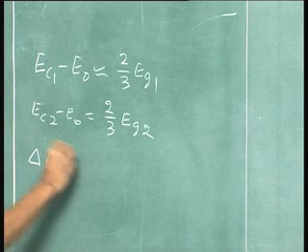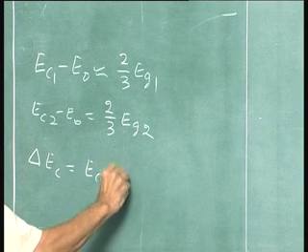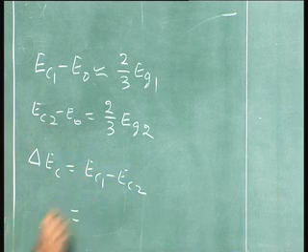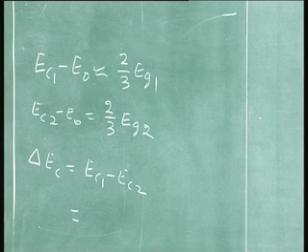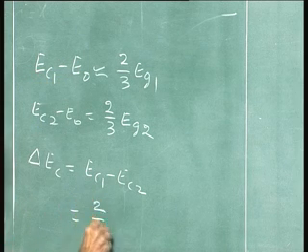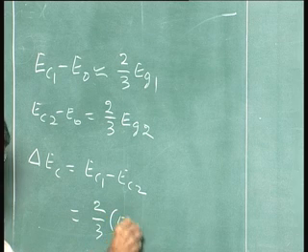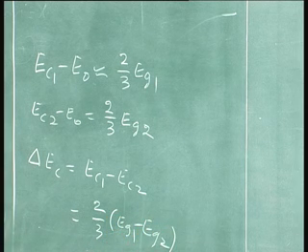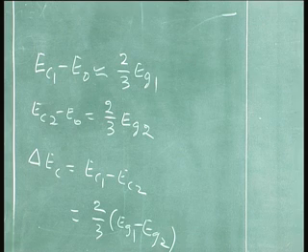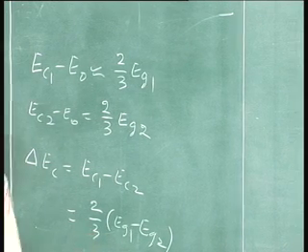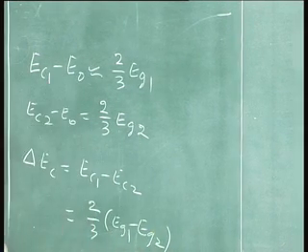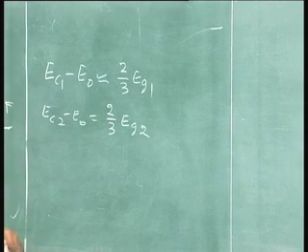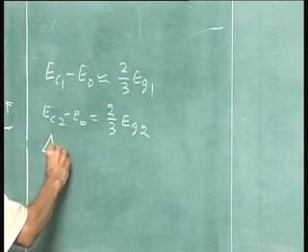Now, what they have seen in experiments is, you can go back and see, almost 0.6 to 0.64. So, that depends how much alignment is there between the E naught levels. If it is exactly aligned with that 2/3 E_g, then you will get 0.66 times. It is slightly different from that. That means it is not exactly aligning, it is not possible. There will be some charge transfer that has to take place, because after all it is governed by this. Let us just take further look into this thing.